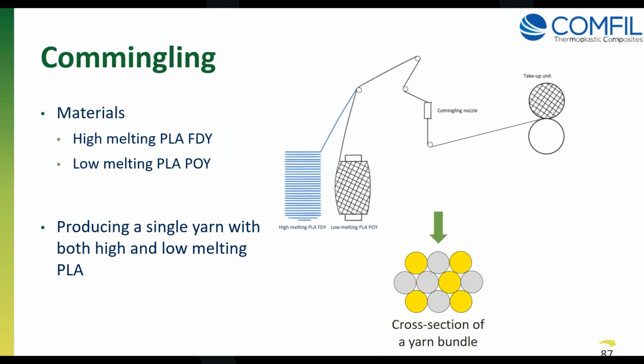So once we have those two filaments separately, then the commingling starts. So we add both materials together in a commingling nozzle to form one thick multifilament yarn. At the bottom here, you can see a cross section where it's just an intermingling of both reinforcement and matrix yarns.